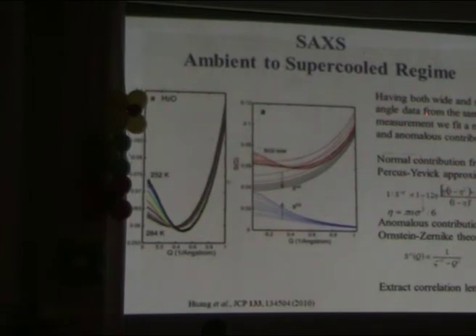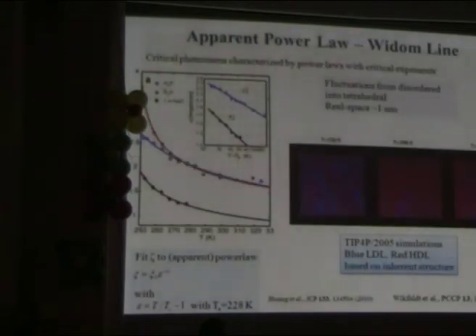Now, what we do here, since we're not focusing solely on the extreme small Q region, but we also go up so we can see the tail of the first peak in the structure factor, this means that we can fit a normal component and an anomalous component. So we can extract the correlation length according to Ornstein-Zernike theory.